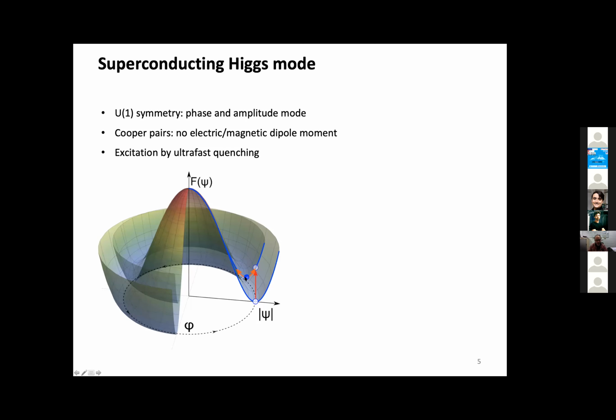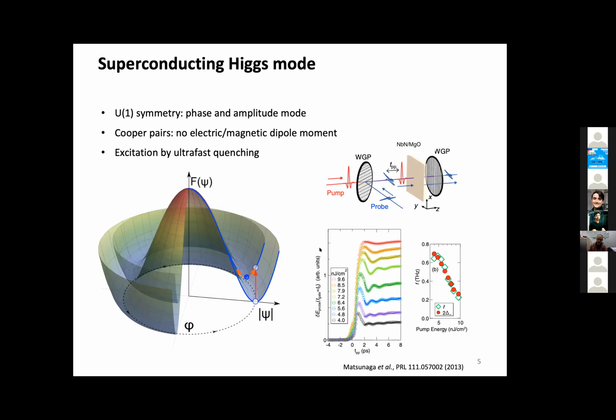So for the people that work in the field of coherent phonons, that looks really very much like an impulsive or displacive excitation of a coherent phonon. The only difference now is that the oscillation frequency here is not given by the phonon frequency, but the Higgs theory tells us that this eigenmode here is now oscillating with 2 times delta of the superconducting gap. And experimentally, in an s-wave superconductor, these kind of Higgs oscillations were first seen by Ryo Shimano's group back in 2013 on niobium nitride, which is an s-wave superconductor.